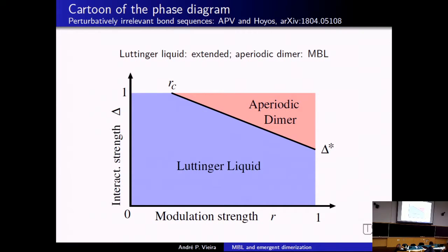But it's important to tell that the non-interacting case here is extended even for strong disorder. Even if you take very strong modulation, you don't get the many-body localized phase unless you add interactions.